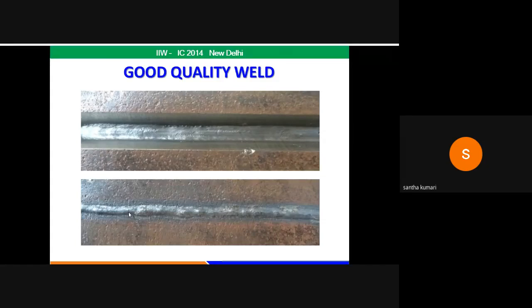The trials are conducted on a 12 mm thick carbon steel plate with a 70-degree included angle in a single V joint. The weld parameters were optimized with solid wire using argon CO2 shielding gas. What is shown here is the top and the bottom of the good weld achieved with the optimized parameters. The top and bottom views of the weld show the uniform bead with ripples and the full penetration achieved.